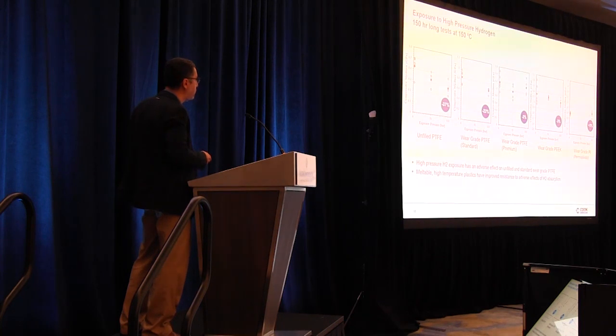So there's something going on with PTFE. And then if we go to a standard wear grade of PTFE, we see a similar decrease. Again, some softening is happening on the PTFE side, some changes in the properties. But interestingly, if we go to the PEEK polymer or the premium wear grade of PTFE, we don't see any kind of a change.